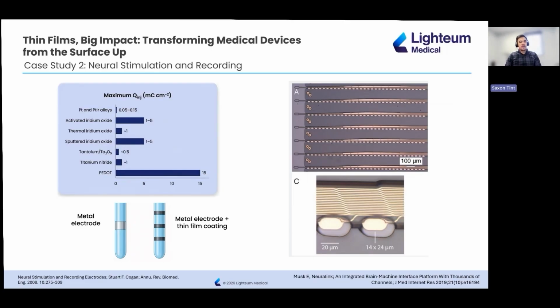This slide shows just how dramatic the effect of these coatings is. On the chart on the left, at the top, is charge injection capacity for different electrode materials. Compare the bare platinum iridium to charge injection coatings like iridium oxide, titanium nitride, and especially PEDOT. The difference is not incremental, it's orders of magnitude. Higher charge injection capacity and lower impedance.